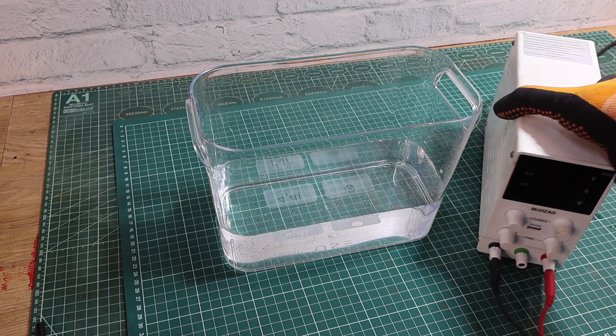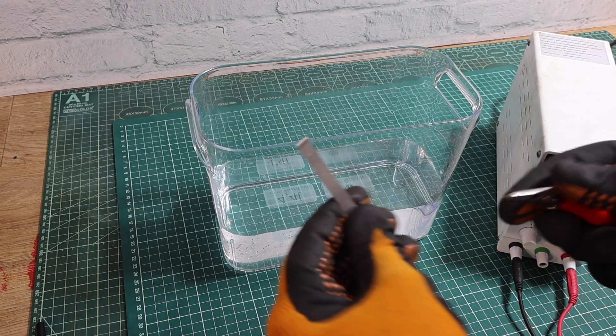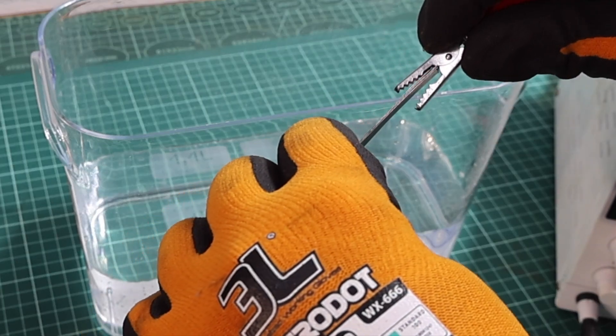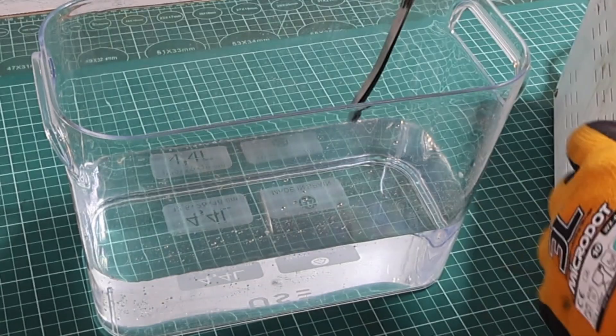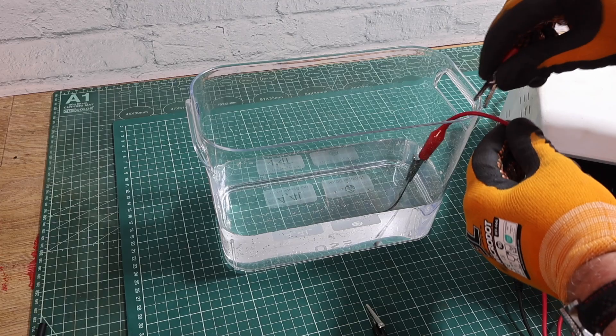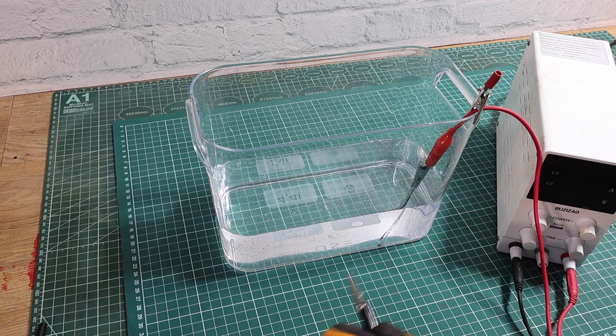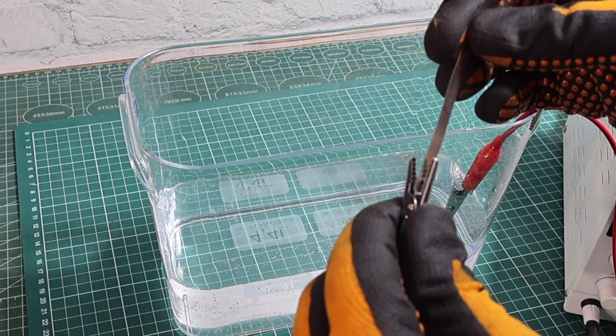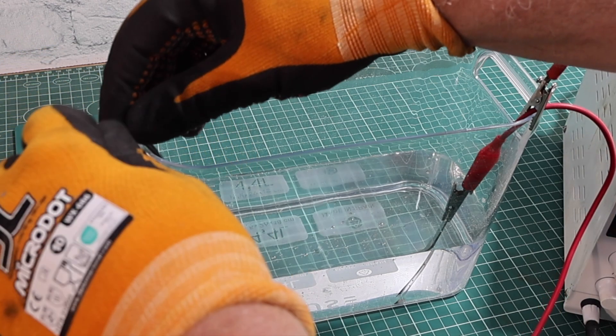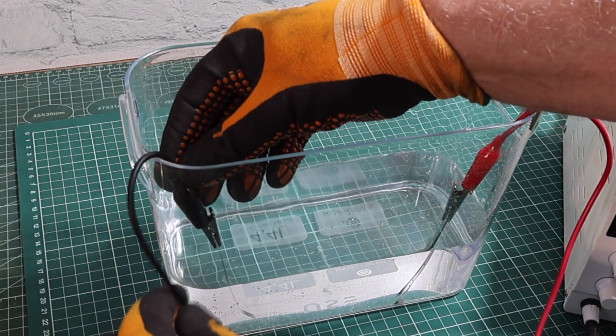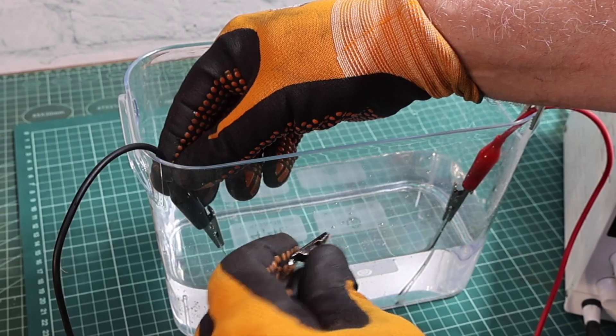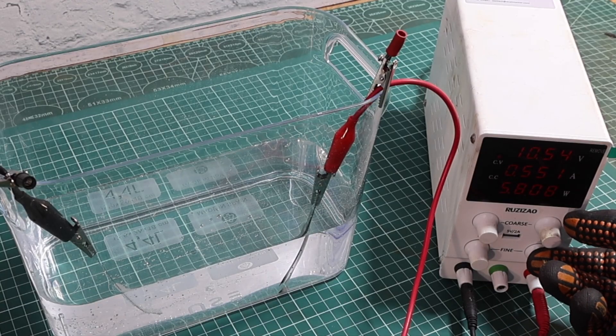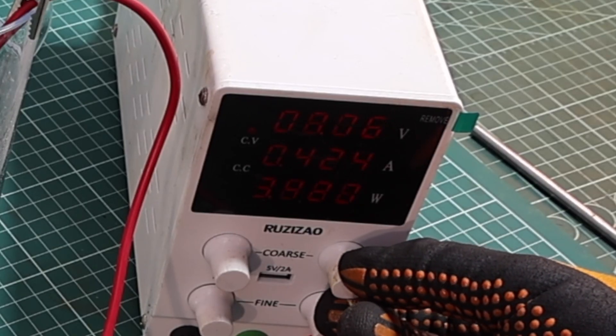There's our power supply. So what we're going to do is we connect up the positive to a bunch of these nickel strips. These nickel strips are easily available on Amazon. You need a relatively high purity and there are lots of sizes available. And on the negative side, we're clipping one. So we're not going to erode these. The positive side is where it's going to erode those nickel strips to make our plating solution.